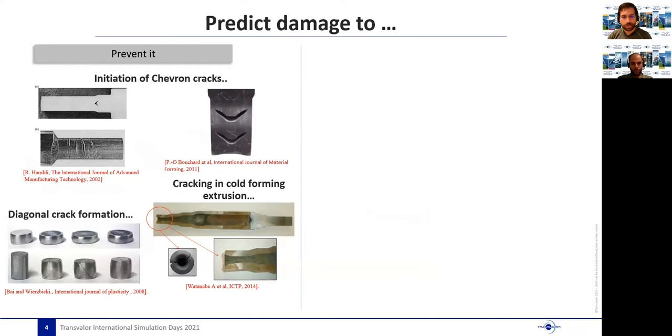When talking about manufacturing of solid-state materials, it is more often than not a synonym of plastic forming in order to obtain some predefined shape. And when talking about plasticity in metallic alloys, damage is usually unavoidable. Nonetheless, damage and fracture are two separate aspects. While some amount of damage can be tolerated without degrading the quality of the final part, fracture means that the structural integrity has already been compromised. It is usually visible as macroscopic cracks, but sometimes these cracks can be very small or even start in the bulk of the material internally. Hence, the need for proper prediction of damage to fracture transition.